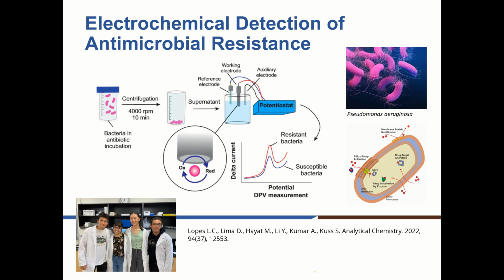Then we give the bacteria time to take up this drug, and then we centrifuge the solution to separate the supernatant and the bacteria. Our hypothesis is that if bacteria are resistant to tobramycin, they would either not consume this drug or expel it after the consumption, basically leading the drug back into solution, and we would obtain a higher electrochemical signal than in susceptible bacteria, which would consume and retain this drug and would be removed together with the drug from the solution.